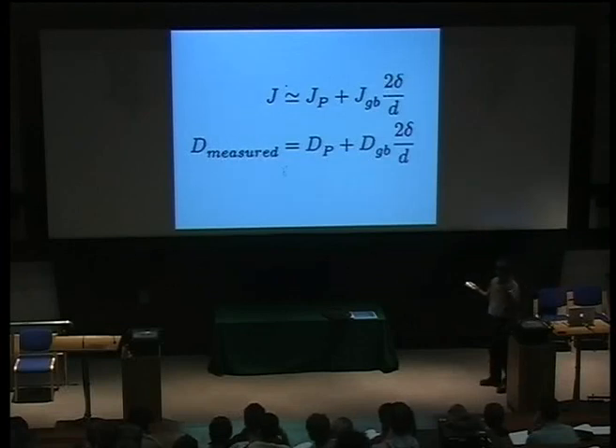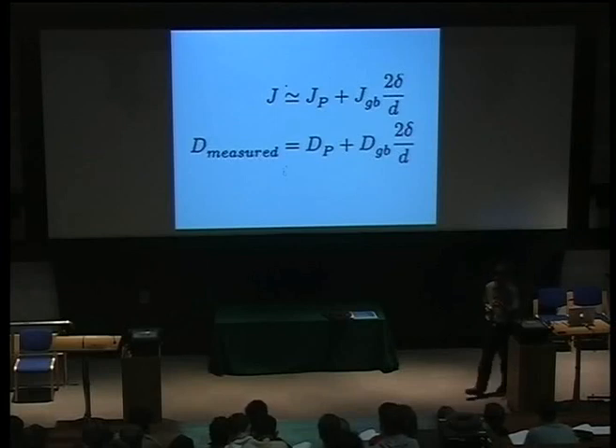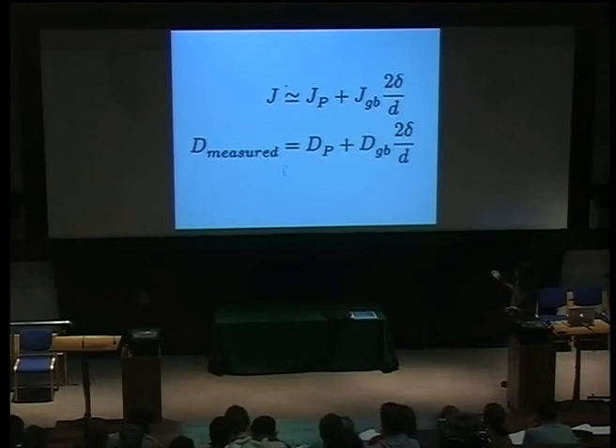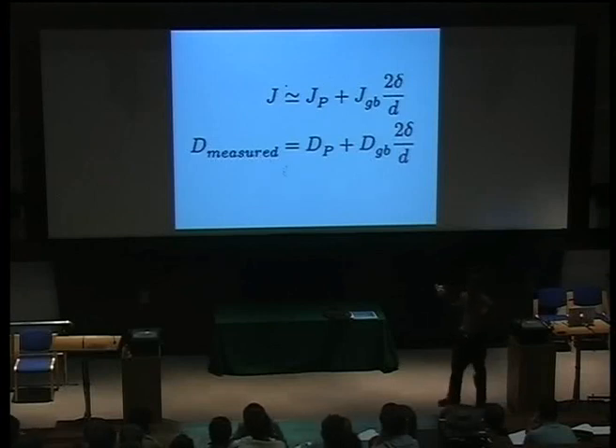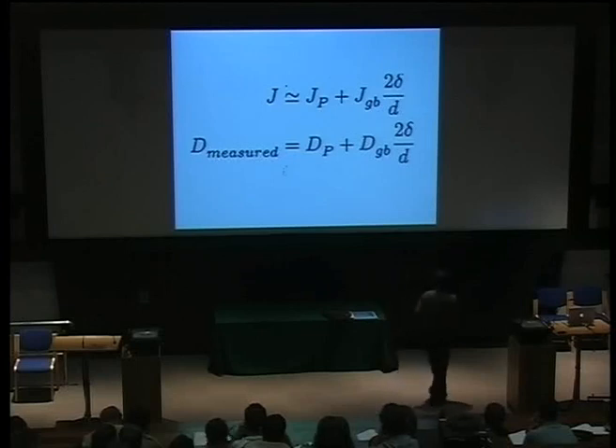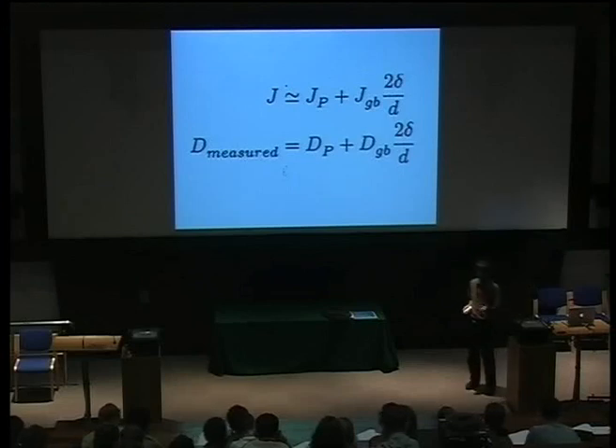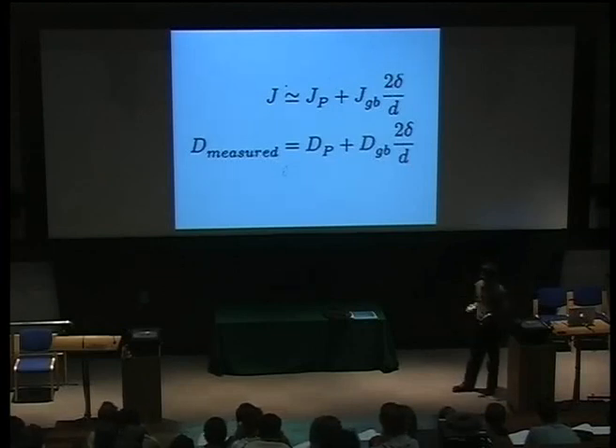Looking at the flux through the plane, there is a flux through the perfect region of the crystal (subscript p) and a flux through the grain boundary (subscript gb). We scale these fluxes according to their areas. Strictly, there should be a term (1 − 2δ/d) multiplying the lattice flux, but in most circumstances that's so close to one that we ignore it. For nanocrystalline metals that term is no longer negligible, and you find the actual diffusion coefficient depends on diffusion through both the perfect lattice and the grain boundary, weighted by the amount of grain boundary present.